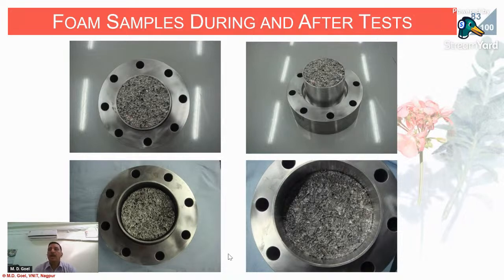Using those pressure gauges and sensors, we collect the data and see how much energy is absorbed. And the interesting part was that until before this test, we understood that all of these samples will absorb the energy. They will not cause an enhancement in the incoming energy. But many times when we did this test, we were surprised to find that at a particular level of loading, they were causing an enhancement of the reflection rather than a reduction in the loading. That was a very interesting point, and that led to an understanding of the importance of such a test.